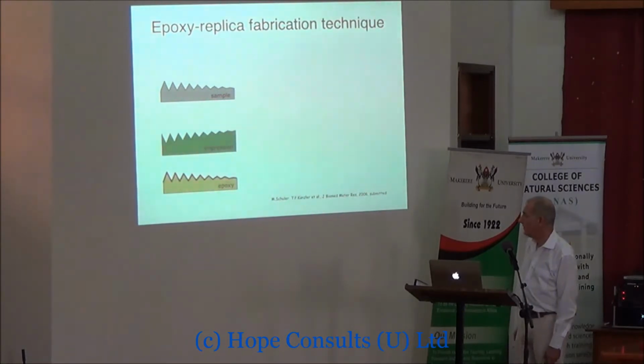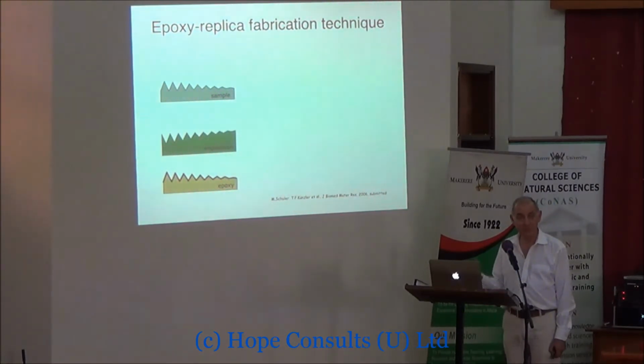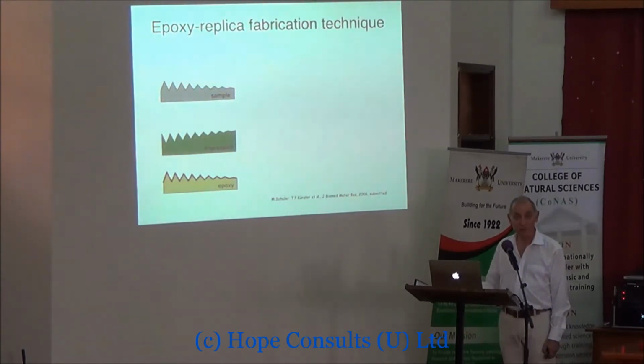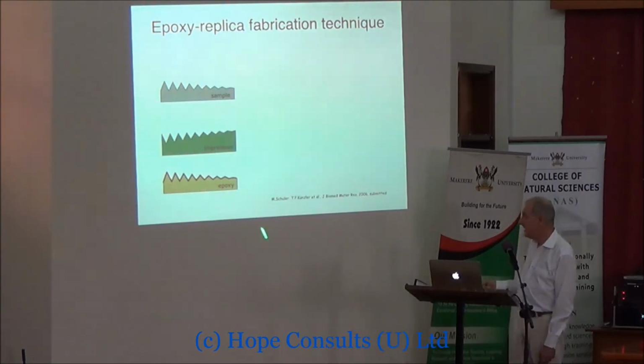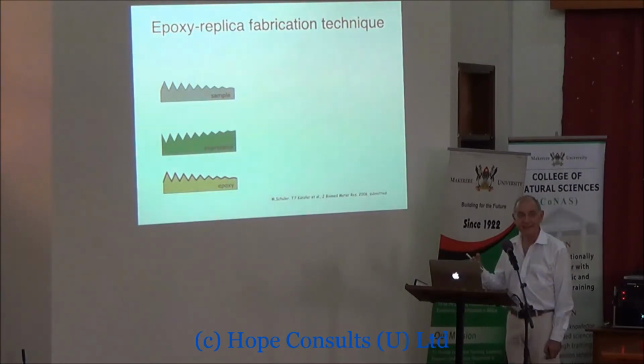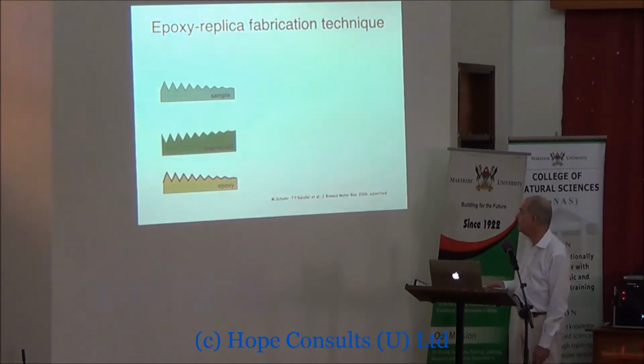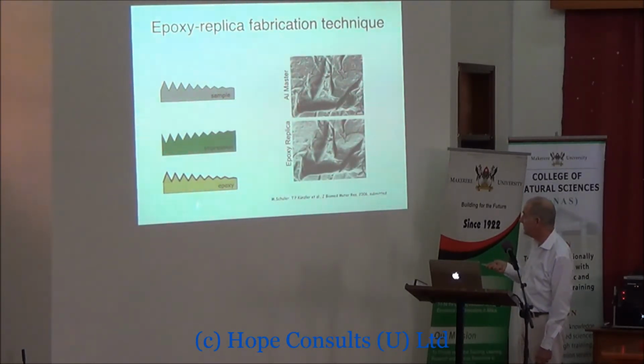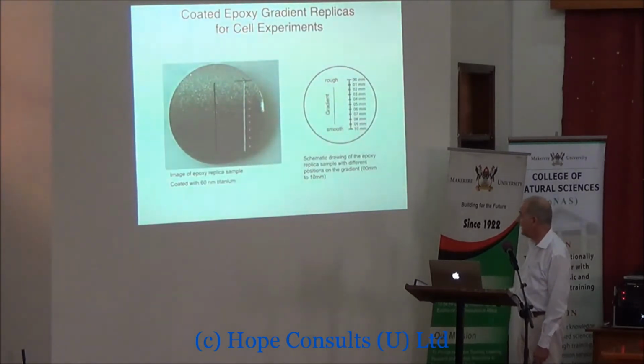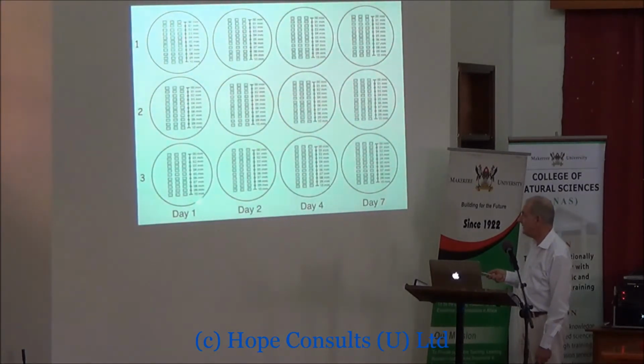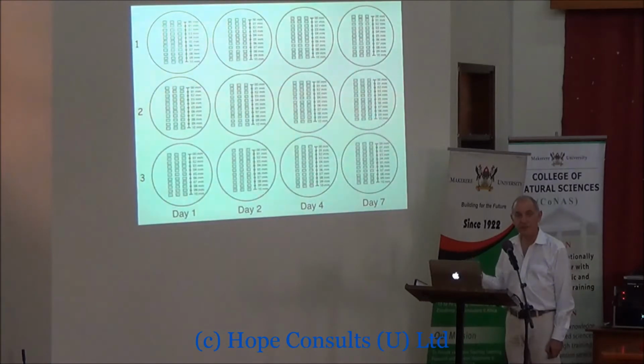And we sputter coat it with titanium oxide to make it look like a titanium oxide surface, which is what you have on the surface of an implant, which is made of titanium. It has a natural titanium oxide surface. So this has the surface chemistry of a titanium implant, but it has our predefined morphology gradient. And we can make as many of these as we like from the original master. So we can make identical but still stochastically rough surfaces with a roughness gradient. And you can see the reproduction with the replication technique is very effective. And this is one of the replicas that's already been coated by 60 nanometers of titanium, and we made loads of them. On each replica, we then measured at 3 points at each roughness value, and so we got lots of data that we could then do statistics on.